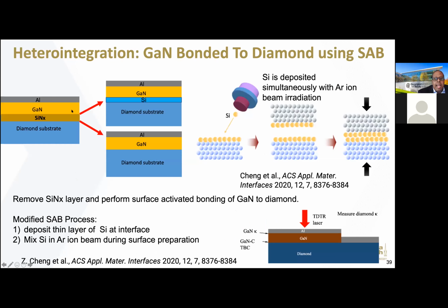And so here's an aspect of taking gallium nitride. We want to remove the silicon nitride, and we want to bond directly to diamond. Well, that's actually not so simple. So what we try to do in working with our collaborators is place a layer of silicon on top of the GaN, a layer of silicon on top of the diamond, plasma activate that and bond it, or you mix a silicon containing precursor in the plasma, so you sort of co-deposit the silicon while you're activating the surfaces and bond. And so again, this is work that was just published last year. And so we're able to successfully bond the materials together that way.